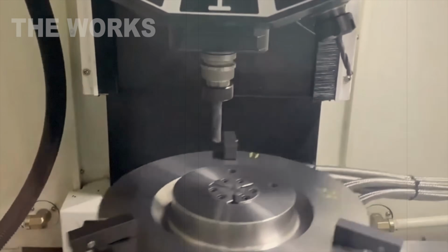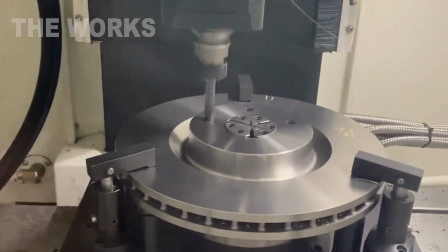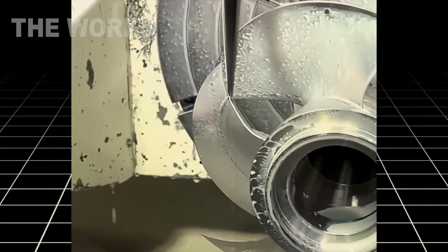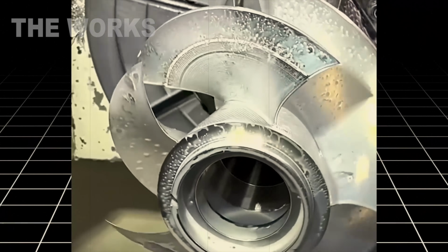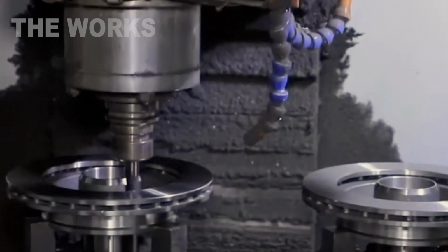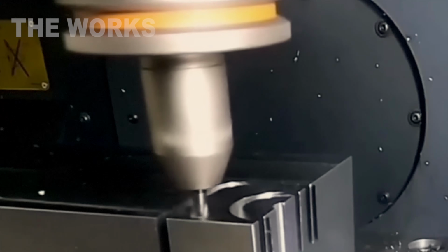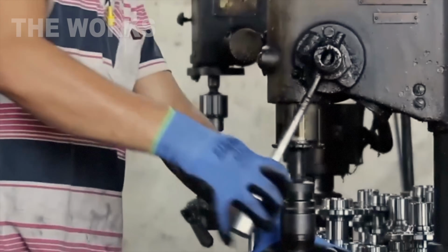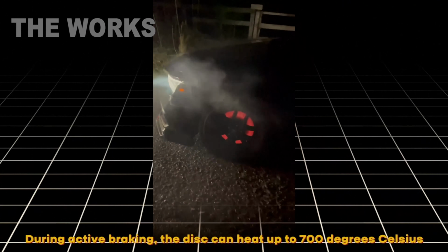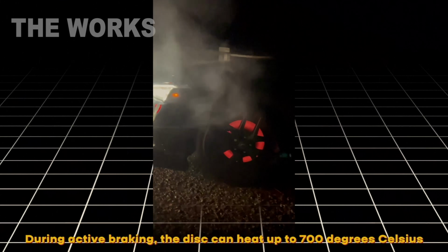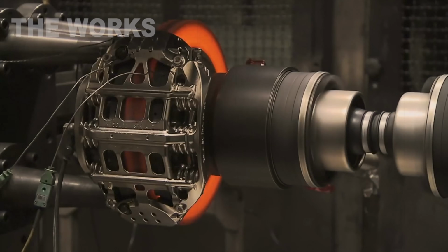Then they drill ventilation holes and internal channels into the discs. This isn't done for visual style like some people think. It's a critically necessary cooling system, without which the disc simply wouldn't survive serious loads. During heavy braking, the disc can heat up to 1,300 degrees Fahrenheit. At that temperature, it glows dark cherry red.